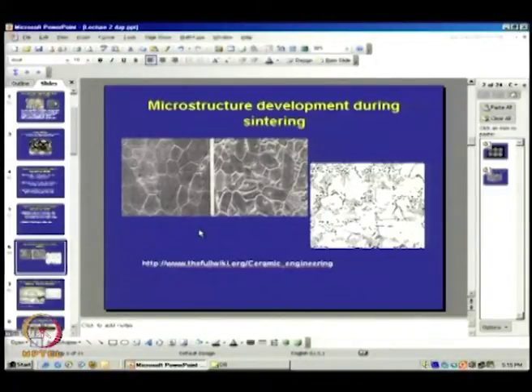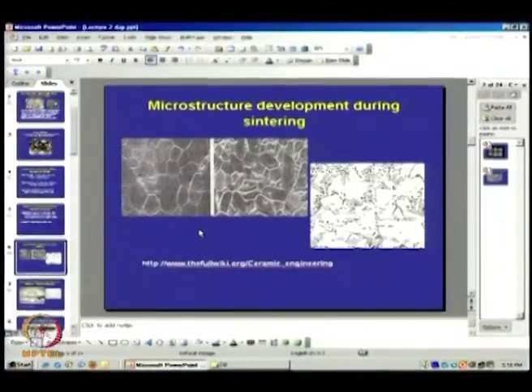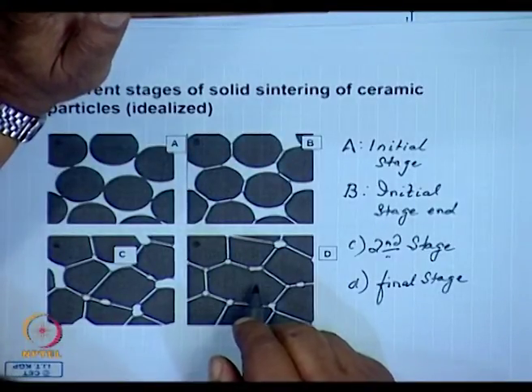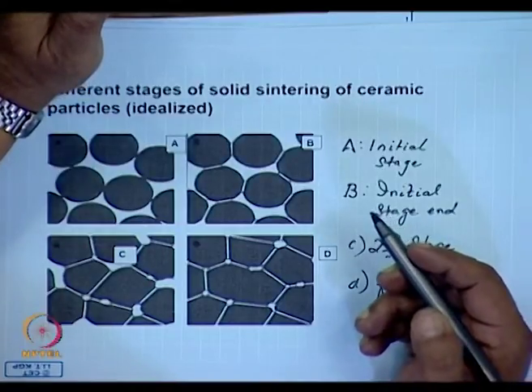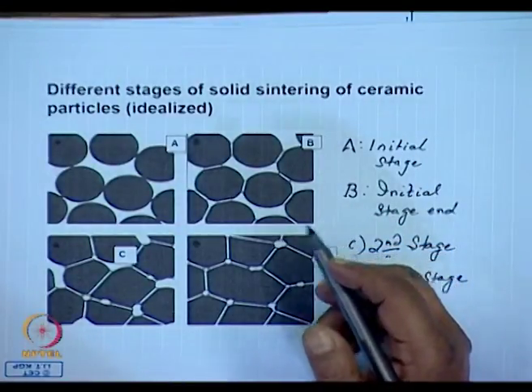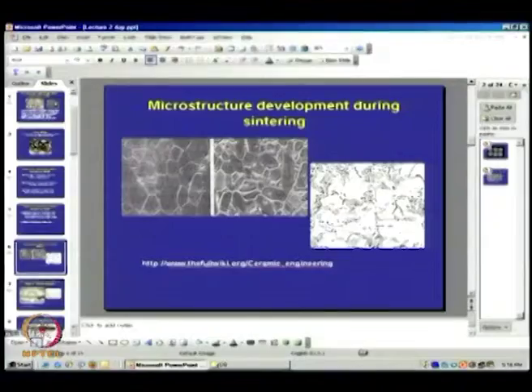But in most cases, what happens is, due to the grain boundaries moving very fast, pores tend to get included within the grains, as it has happened over here. In this particular microstructure, the pore is within the grain because the grain boundary has moved very fast. The pore did not have time to be removed, and as a result, all these closed pores are within the grains. This is a necessary hazard of sintering.